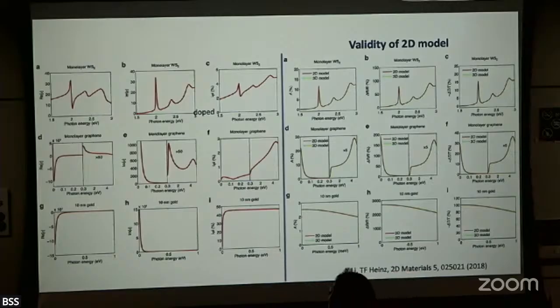For the imaginary part, you see some kind of a funnel-like line shape, and that's due to interference of these discrete levels with continuum. So the column C is important. If you look at the values, it says a few percent. So phi is small. So in this case, the highest is about 0.05, right?